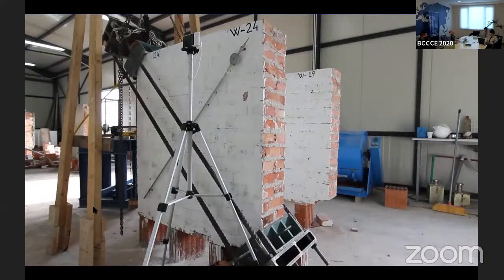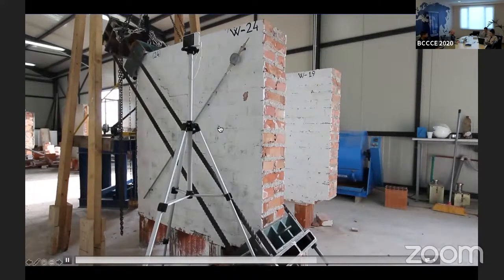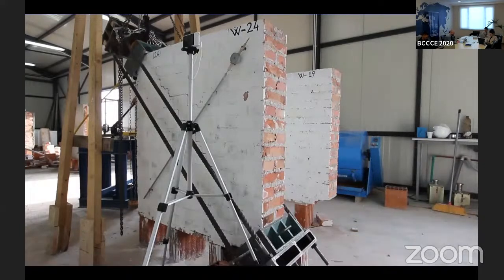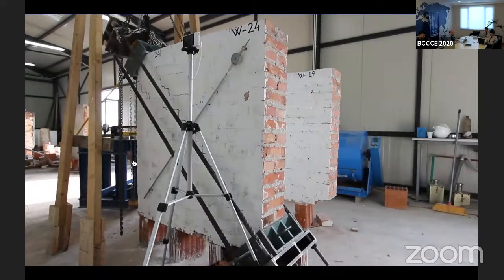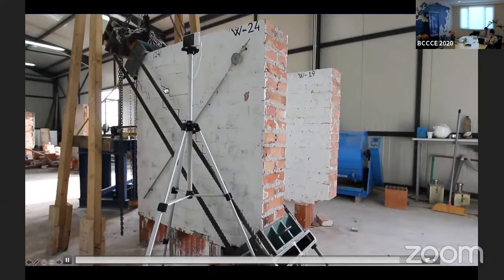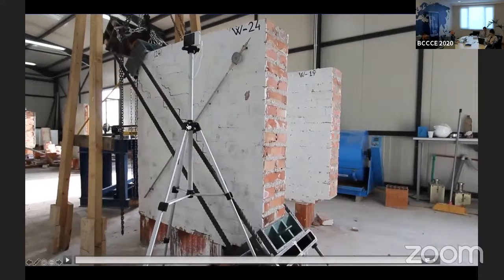So as you can see, now it starts to be seen, a diagonal crack along the compressed diagonal until the load will, until the wall will fail completely and will not carry any more load. As you can see now, the diagonal is more visible, and it's not only along the main diagonal, but it spreads also parallel to that one.